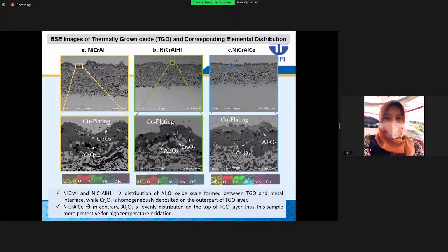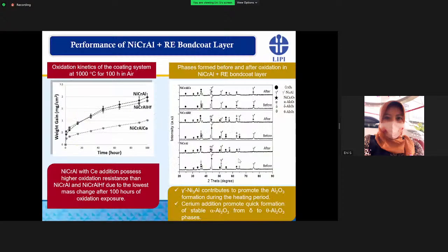The chromium oxide is homogeneously deposited on the outer part of the TGO layer. On the contrary, in the nickel, chromium, aluminum with the cerium addition, alumina is evenly distributed on top of the TGO layer. Thus, it seems to be more protective for high temperature oxidation. Therefore, we tried to oxidize the samples at a temperature of 1000 degrees C for 100 hours.